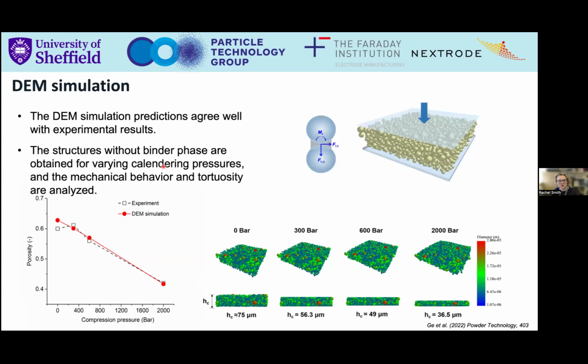And what we do then is we say, okay, we've got a tomography scan of a pre-calendared electrode, and we've got a tomography scan of a post-calendared electrode, and we see that change in the microstructure. So we captured that here by using the porosity of the structure that we have. And so we ran simulations, and what we found was we got quite reasonable agreement here between the porosity of the structures and the compaction pressure in the electrodes.